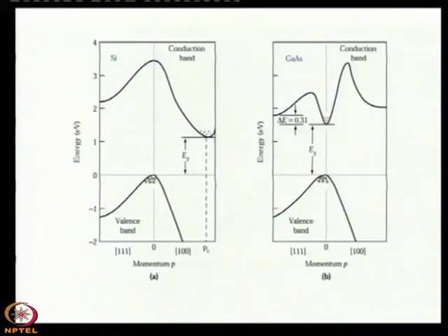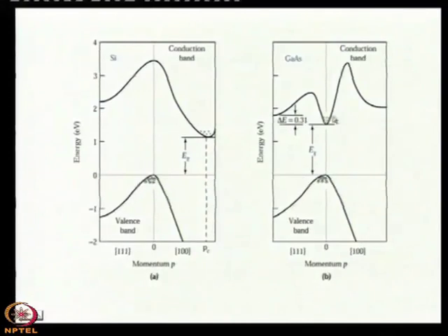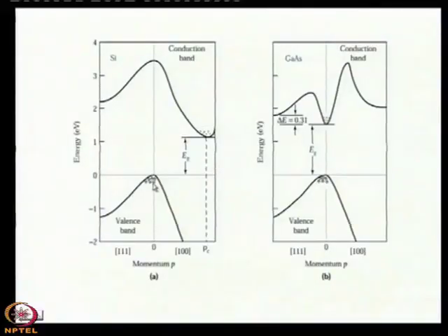Okay, what will happen here? Here also the electrons are at K0, the holes are also at K0, but the electrons' original residence was where? In the valence band. So, when you excite the electrons by some means of energy from the valence band to the conduction band, basically the electrons are energized. So, they will come down to the valence band, but the problem is that momentum conservation is also required. Here they can jump down, but here they cannot; with the help of a trap level they can come. And now, where will the momentum go? Obviously, the momentum will be conserved with the help of Et. So, Et and the electron will form a system where the conservation will take place, but that is not related to your valence band holes. So, no movement is there.